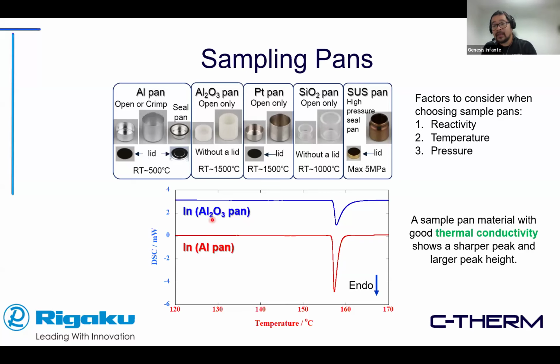So, for example, ceramic type crucibles have a lower thermal conductivity, something like an aluminum, right? So you can see here that the signal is a little bit broader, less sharp as compared to the aluminum, because the heat is going to be conveyed across the pan in a slower manner. So if you get the area under the curve right here, it's going to be equal to each other. It's just that the sharpness and the resolution will be a little bit different depending on what you use.